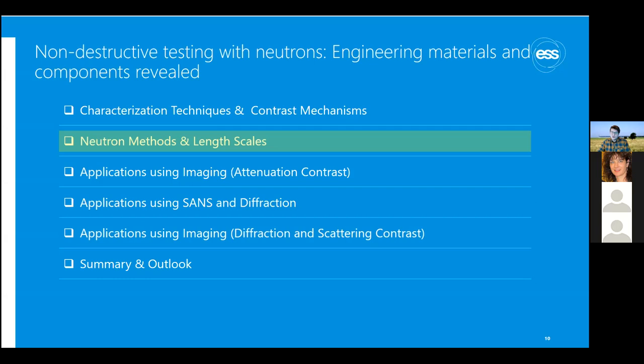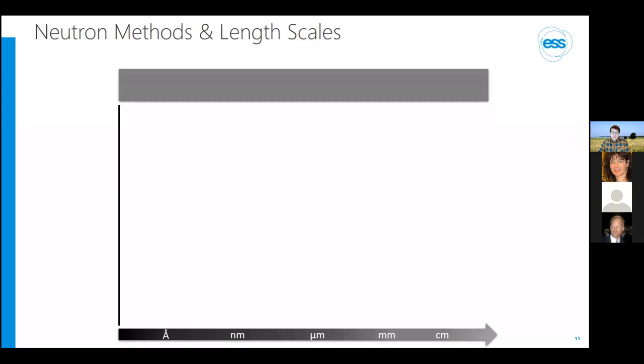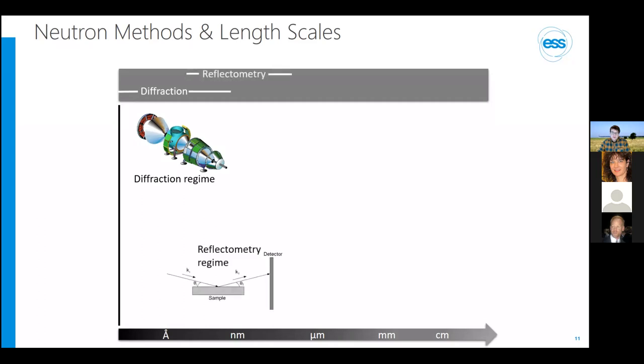Next, I would now like to show you which neutron-based techniques can actually be used to study materials at different length scales. At ESS, we will have a suite of instruments that will offer the most common neutron techniques shortly after we start operating the facility. Here you can see a very rough range of length scales on the x-axis. If you are interested in the atomic structure and or the magnetic structure of materials, then atomic lattice spacings on the angstrom regime can be probed by neutron diffraction, while neutron reflectometry is a very powerful technique to investigate surface and interface structures on length scales ranging from the sub-nanometer up to several hundreds of nanometers.